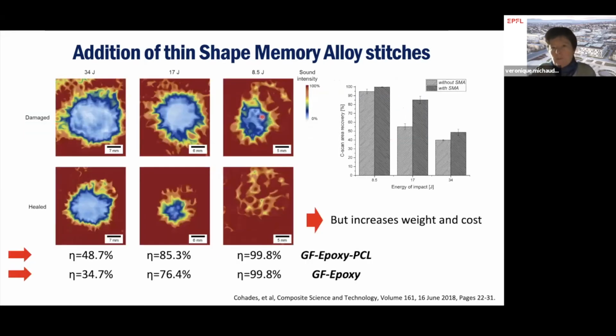We also checked this for small cracks. So after impact on those shape memory alloy stitched plates, we had a very good healing efficiency. And we see that compared to the ones without the SMA stitches, we also had a much better healing efficiency at moderate impact energy. However, this is not really a suitable solution because it can be used only in specific areas, and it increases a lot the weight and the cost. So what to do next?